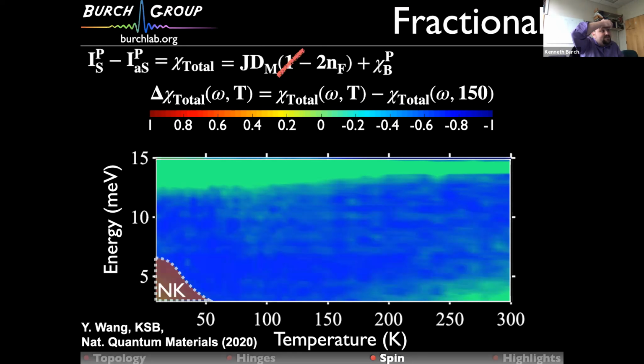It's basically very similar to what Ming would deal with, except that in my case I create pairs, and so I have the square instead of just 1 minus. And the reason you create pairs is fundamentally because you can think of the Raman process as flipping a spin, and so it creates a pair of Majoranas. In reality, it's actually exchanging spins between different sites, but essentially that's what's going on. Yeah, that part is roughly speaking the same as neutrons.